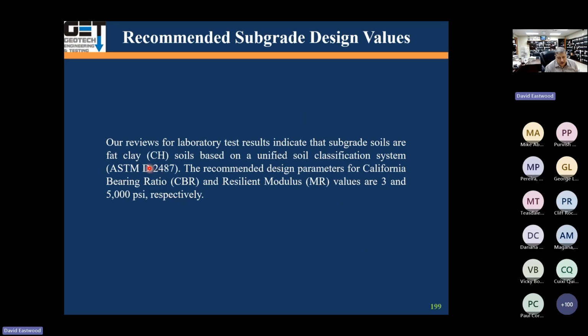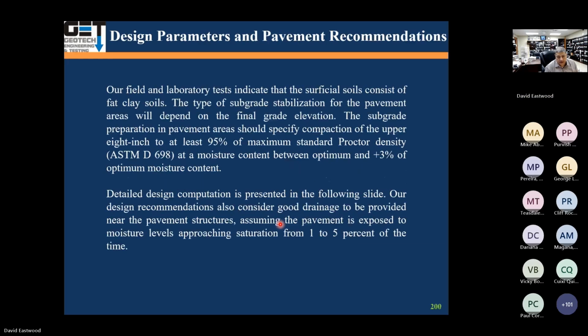Of course, the soils underneath the pavement were fat clays. Looking at the AASHTO pavement design, the resilient modulus was 5,000 PSI. CBR was 3. Resilient modulus is usually about 1,500 times CBR, that's California bearing ratio. We ran a bunch of tests to see what kind of pavement structure we have, and went through the pavement design by AASHTO.